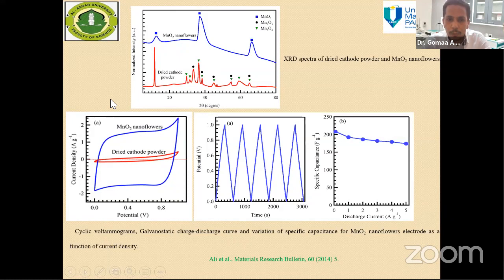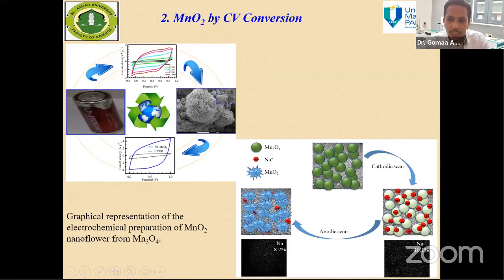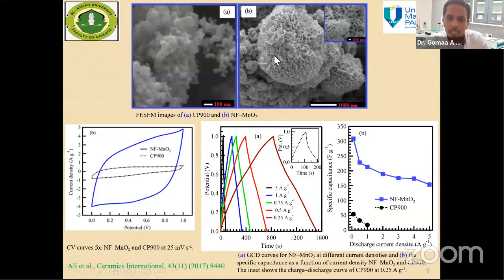From the same source, zinc carbon battery, we recycled manganese oxide by a different method, using cyclic voltammetry, by applying voltage for many cycles, and we successfully converted the cathode powder of the battery into a nanoflower structure of manganese oxide. This is the mechanism during the charging and discharging cycles. We got the nanoflower morphology of manganese oxide compared to just clusters of aggregated particles of the cathode powder. This is the cathode powder before conversion, and this is the manganese oxide nanoflower morphology after applying cyclic voltammetry.